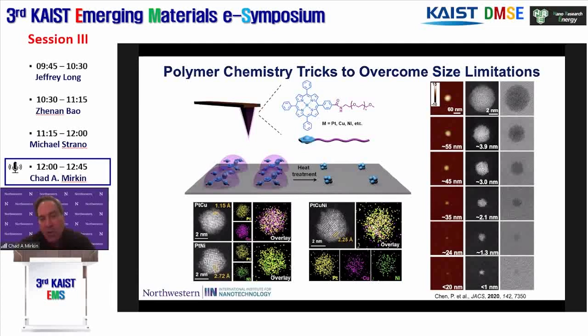So Peng Chen thought about this and he said, the way to narrow this is to synthesize polymers where there's only one group per polymer chain that can hold a metal ion. So he end-capped polymers in this case with a porphyrin group that could be loaded up with any metal of interest. And now, literally, the number of polymer chains you incorporate into a reactor will dictate the number of metal atoms that go into particle synthesis.